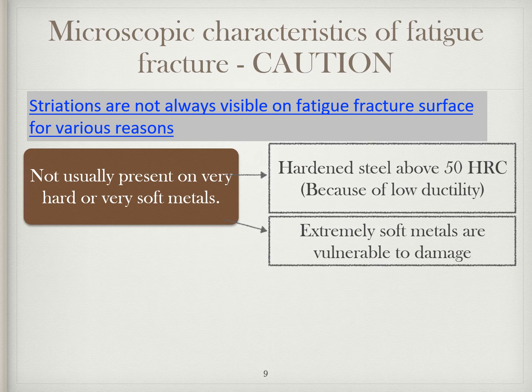While interpreting the fractured surface for fatigue fracture, the failure analysts need to be cautious. Striations are usually not present on very hard or very soft metals. Hardened steels over about 50 HRC develop either poorly formed or no striations, probably because of their lack of ductility. As hardness increases, striations are more difficult to observe, often resulting in fractured surfaces that appear to be featureless.